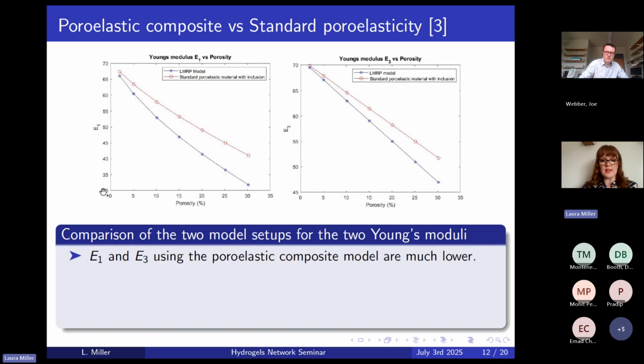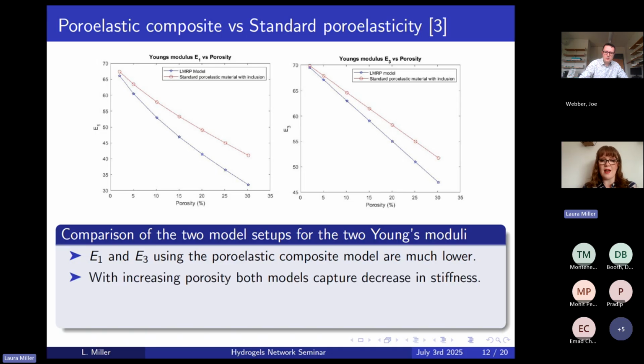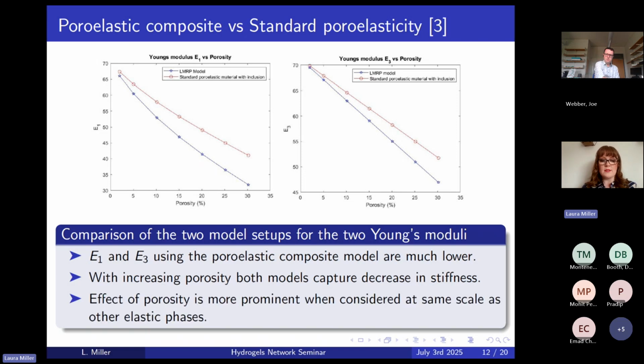So we just did a test case where we were increasing the porosity because we wanted to understand what role the porosity was having on the stiffness that we could capture with both models. So we are seeing that the effect of the porosity is much more prominent when it's considered at the same scale as the other elastic phases. Now, this is probably what we would have expected, but that's actually reinforcing the necessity of our model, because with what was already in the literature, you can't have two solids and a porosity at the same scale. You can either have a composite with two solids, or you can have a homogeneous solid and the pores. So that already, before we even really were doing too much of an understanding of what this actual absolute difference was, was reassuring, because you're seeing more of an effect already. And if that's what you've got in your material, that's what you want to be able to find.